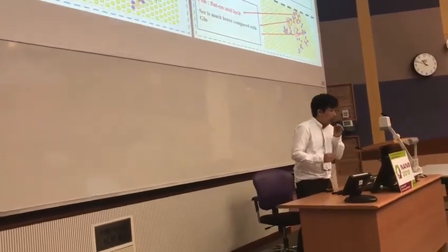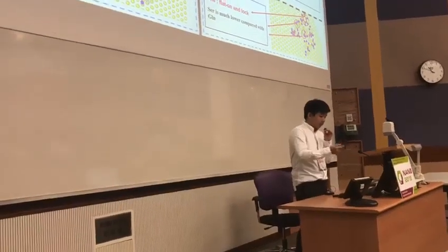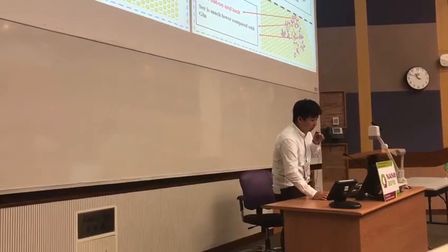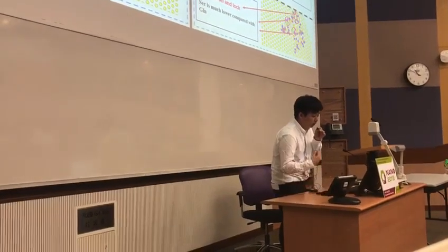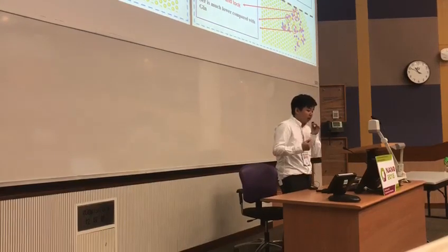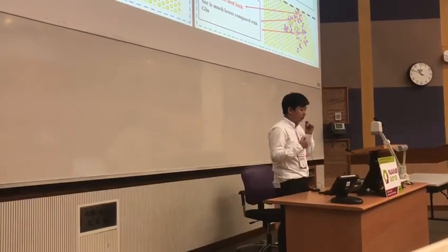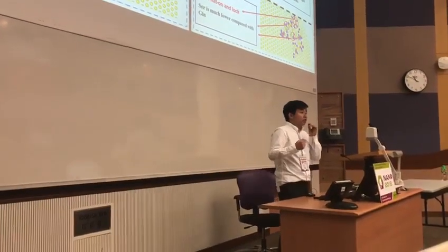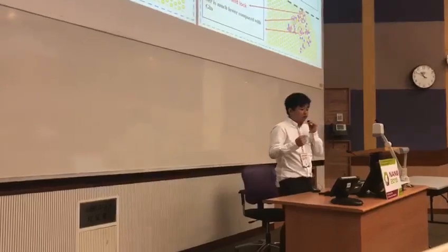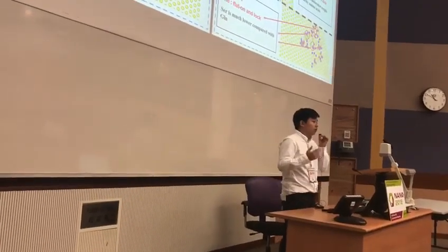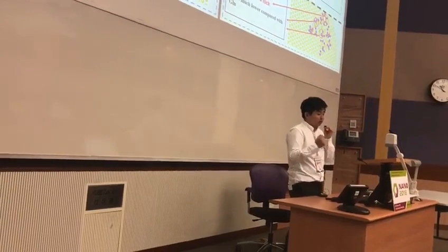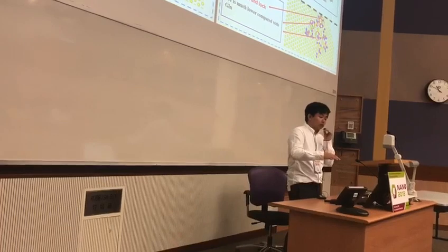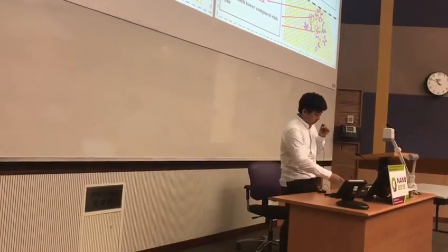And according to variants 5 and 6, we can see the amino acid GLN is a high molecular weight polarity amino acid, and the SER is much lower compared with GLN. So this means the pHE of variant 5 becomes unstable because the GLN and the pHE fight against each other for the adsorption site.